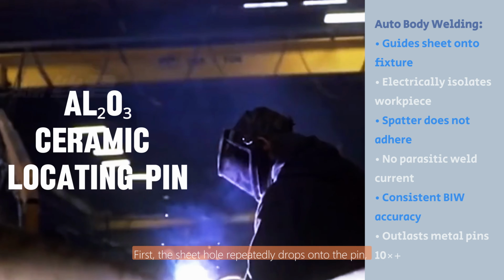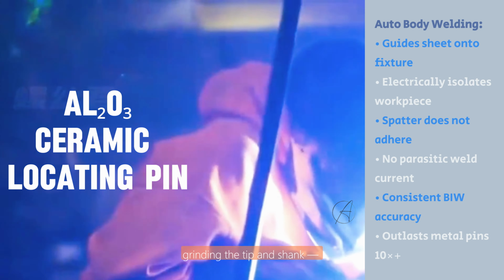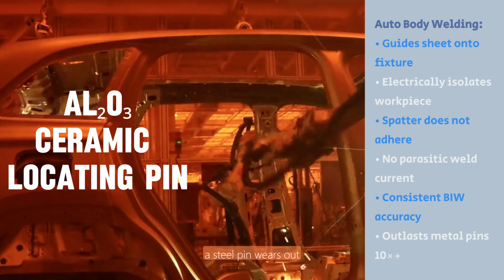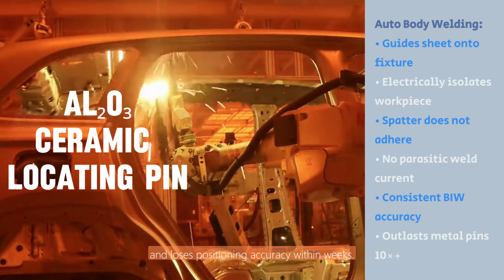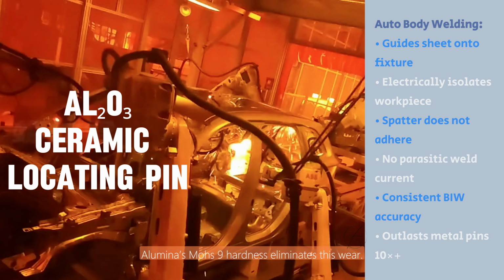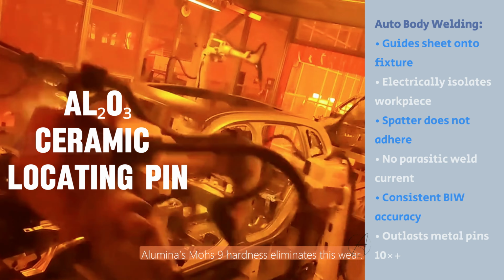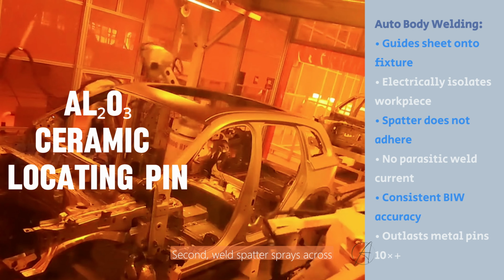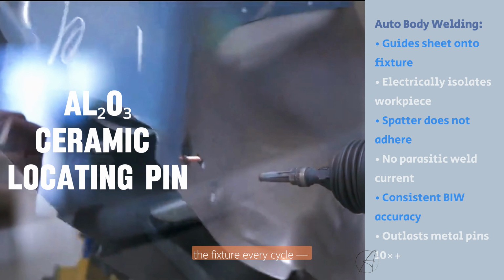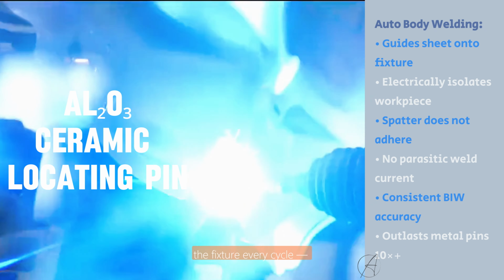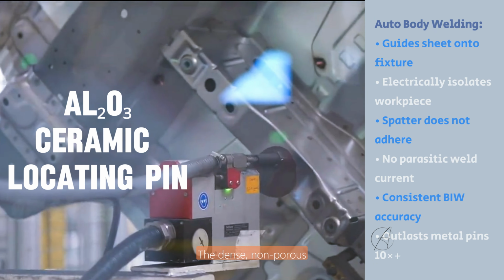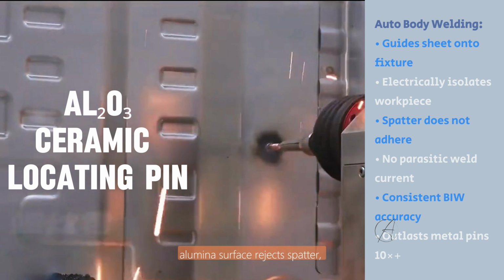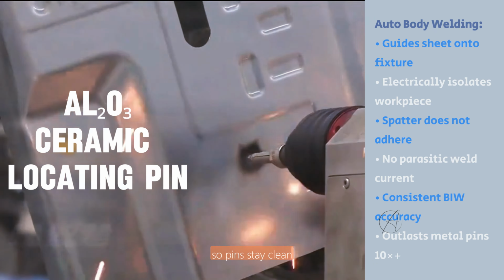First, the sheet hole repeatedly drops onto the pin, grinding the tip and shank. A steel pin wears out and loses positioning accuracy within weeks. Alumina's Mohs 9 hardness eliminates this wear. Second, weld spatter sprays across the fixture every cycle. Molten steel droplets fuse onto metal pins and eventually build up into a crust that prevents the sheet from seating. The dense, non-porous alumina surface rejects spatter, so pins stay clean across entire production shifts.